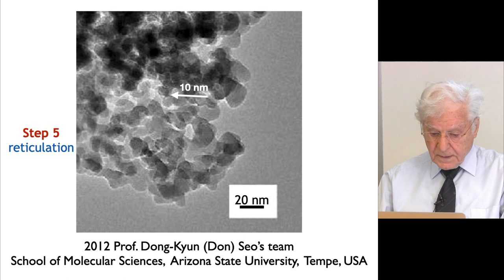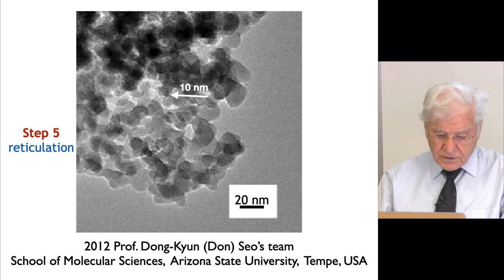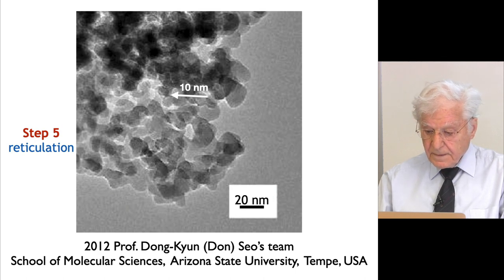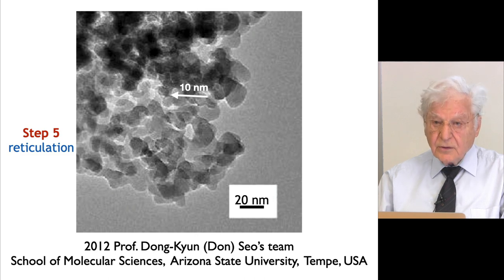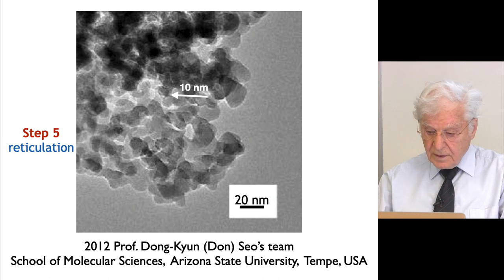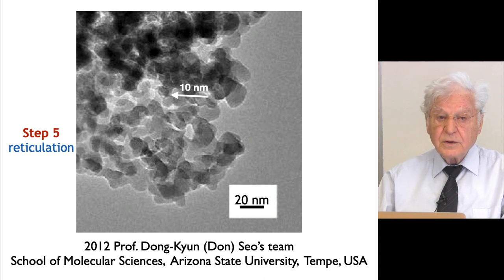9 years later, Professor Dong Kyun Seo from Arizona State University in Tempe in the USA conducted a study with a regular metakaolin-based geopolymer. The scale is now 20 nanometers. During the reticulation process of step five, the geopolymer micelles, which are 10 nanometers in dimension, were clearly visible under observation.